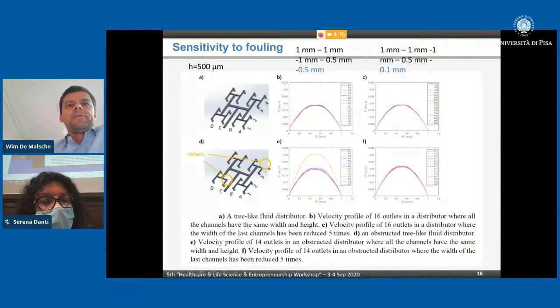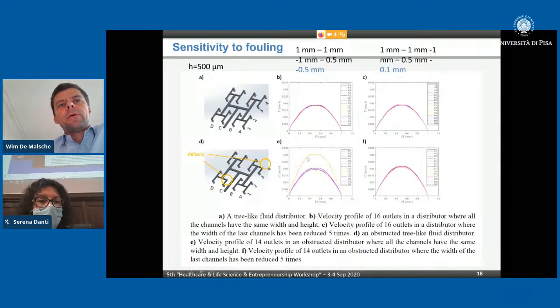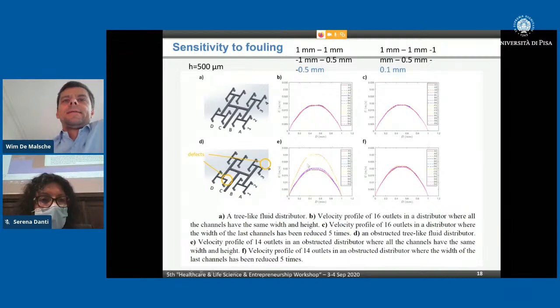If we include one defect, we took away a branch here and one here, you can see that the other branches will give higher velocities. These are average velocities across the exiting hole. And so these are aberrant flow rates, and these will produce larger sized droplets, as you could see a few slides ago. And so this is a problem. When fouling occurs, this is a problem.